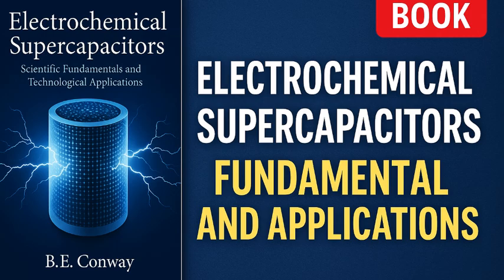By pairing such solvents with salts whose ions are larger and less prone to decomposition, like tetraethyl ammonium cations and tetrafluoroborate anions, which are standard in commercial supercapacitors, we can significantly raise the cell voltage. In fact, combinations of various organic solvents such as acetonitrile, propylene carbonate, gamma butyrolactone, and salts like quaternary ammonium salts or lithium salts are chosen to optimize the voltage window.